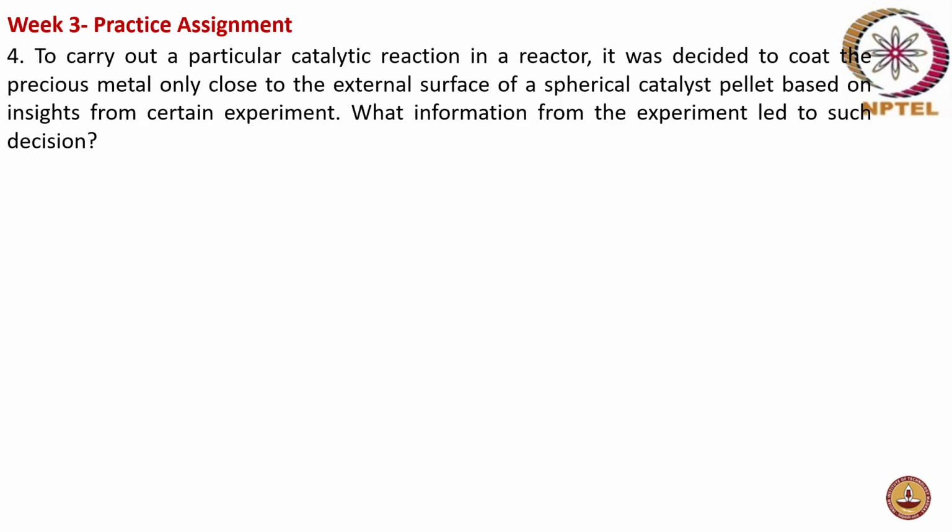So what they have decided is, if you consider a pore, they have planned to coat only near the pore mouth, or to a certain extent near the pore mouth. Only the surface of the pore near the mouth they have planned to coat with the precious metal. They performed some experiment, and from the insight of that experiment, they came to such a conclusion.